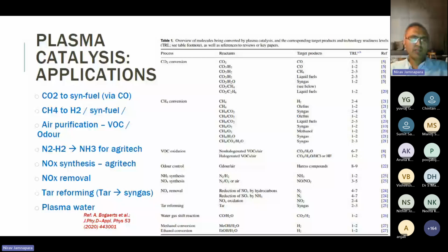The breakdown of CH4 to hydrogen or synthetic fuel is cited. Air purification, VOC odor in other applications. Nitrogen-hydrogen to NH3 for agriculture. NOx synthesis for agri-tech. NOx removal, tar reforming for tar gas to syngas, and plasma water. There are several plasma catalysis applications which can be significantly used. Now here, as you can see, the targeted products have been significantly impacted, and up to 80% conversion has been reported recently. But there are challenges in plasma catalysis.